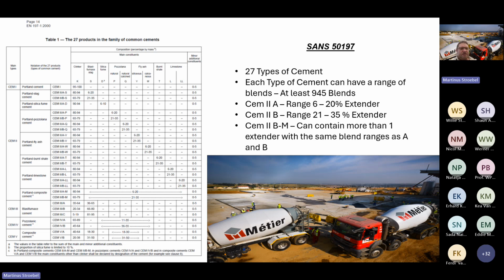And according to SANS 50197, there's a band. If we take the worst case scenarios, a CEM II or a CEM IV B, you can blend up to 35 or more than that. I think it's up to 50% extender in a B mix, which then says there are around about 945 blends that any ready-mix guy or any producer can come up with. The problem with this is each of those blends will have its own strength gain characteristics, and that determines the rate that you can build at.